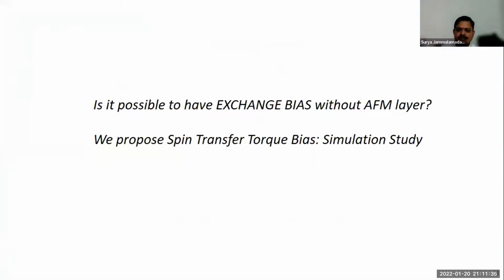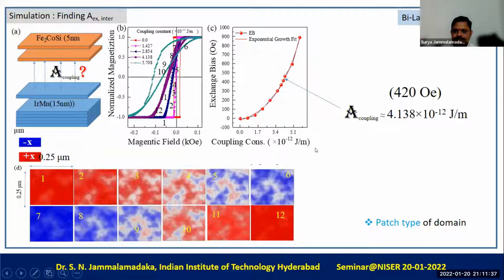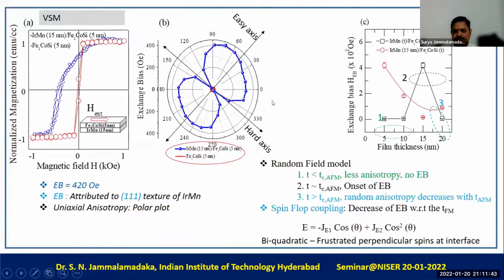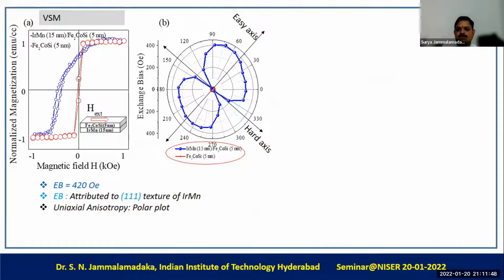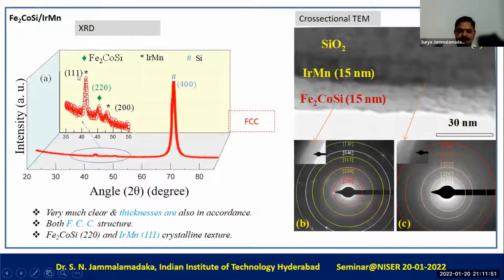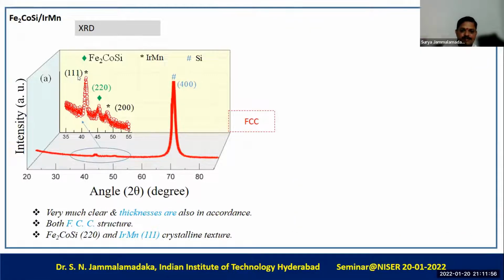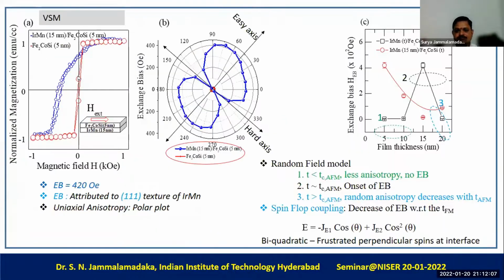So anisotropy exists, just one minute. The anisotropy exists based upon the shape of the polar plot. Suppose you have a circular polar plot, that means it is isotropic. But if you have a lobe kind of thing, that is fourfold anisotropy plus twofold anisotropy. If the lobe expands in four different directions, it is a fourfold anisotropy. If the lobe expands only in this fashion, it is uniaxial anisotropy. So this is how we define the anisotropy in the polar plot.